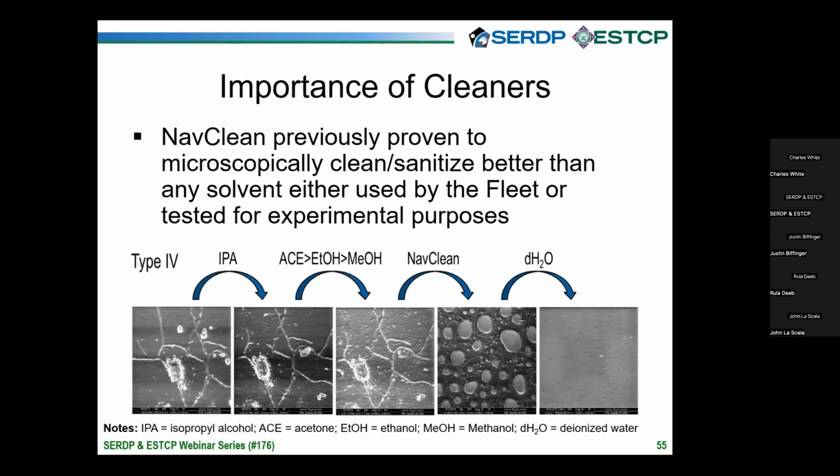The effect of these cleaners on the hyphae are shown at the bottom of the slide on the photos of the last three. Those images that look like cracks in the coating are the long filamentous growth, or hyphae, that will result in rapid regrowth if not removed.